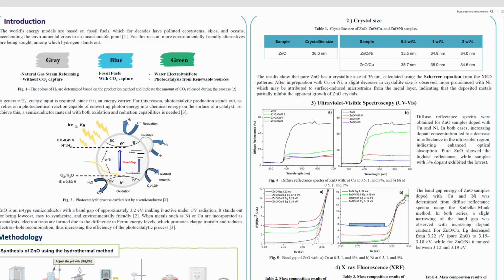In this case, we used hydrothermal synthesis. Well, once the external energy is applied, as you can see next, if the applied energy is sufficiently great for its specific band gap, we excite an electron from the lower valence band to the higher conduction band, thereby initiating a crucial electronic transition.